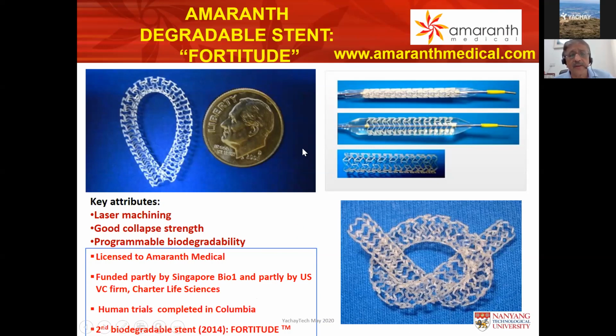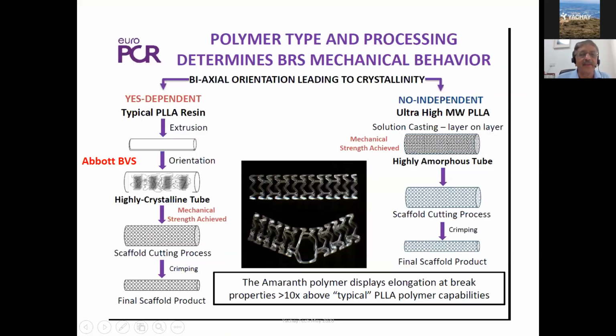But unfortunately, the story of biodegradable stents took a bad turn with the problems that were associated with the very first biodegradable stent called the Abbott Vascular BVS stent that was developed using a crystalline form of PLLA, polylactic acid. They developed it by extruding the PLLA resin, orienting it, and then forming a highly crystalline tube, which was then cut according to the femtosecond laser process and then crimped onto the balloon. Amaranth, in contrast, developed what is called an ultra-high molecular weight PLLA polymer, which was not fully crystalline. In fact, it was highly amorphous, which led to very tough properties with very little breakage, as I will show later. But the scaffold cutting process and the crimping process were similar to the Abbott vascular stent.